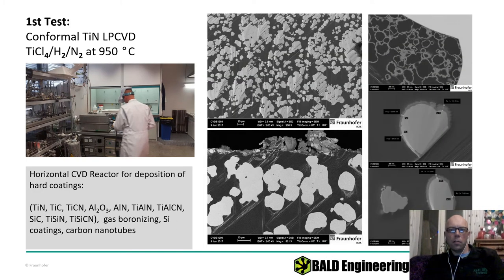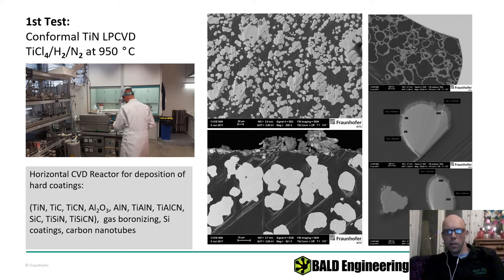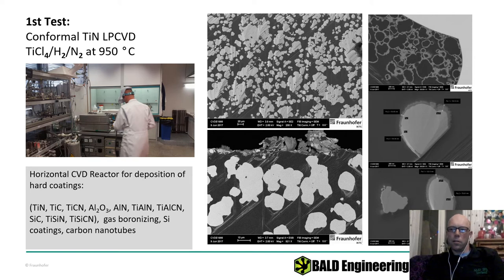We got coverage, and it's quite decent — quite nice and conformal. You can see the light coating around the darker tungsten carbide grains. However, sometimes you had a shadowing effect — thinner coating on one side and thicker on the other. So it's not perfectly conformal, which means we definitely need to try ALD instead. We want to do it perfectly.